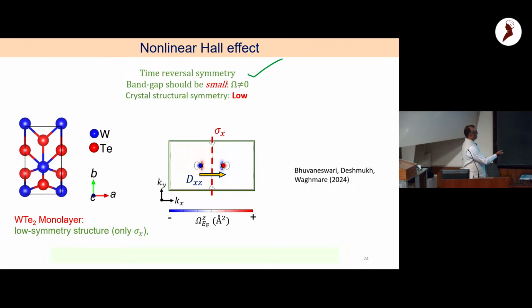And basically, Bhuvaneshwari looked at a monolayer of tungsten telluride and used quantum calculations to show that you have a Berry curvature with a dipole moment, or first moment, in reciprocal space because of the specific mirror plane. The mirror symmetry basically means the crystal should have only one mirror plane. If it has two mirror planes perpendicular to each other, you get zero dipole moment again. So for this effect also, symmetry is a constraint.